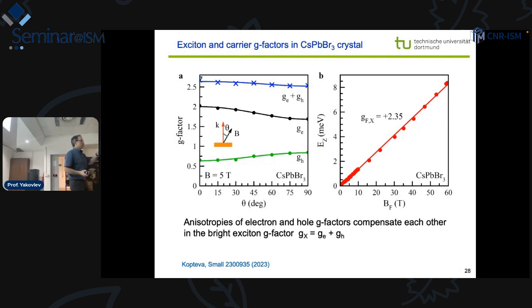Whatever you do with the electron and hole g-factors separately, when they are put together, they give you the same isotropic value. So this is an example where we measure the exciton g-factor up to 60 Tesla in pulsed magnetic field in Los Alamos. The dependence is very straight, monotonous. It's also a result of the bands being very simple, so there is no admixture of additional bands even by such high magnetic fields, as the spin orbit state is far away.